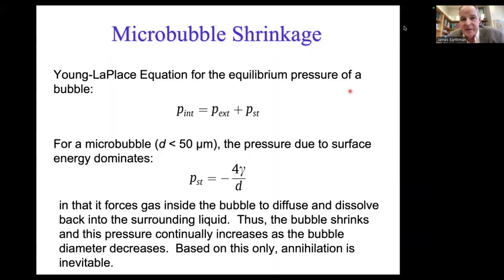The explanation for this is provided by the Young-Laplace equation, where you can see for equilibrium pressure of a bubble, you've got internal pressure, you've got external pressure, and then you have this surface tension pressure here. And again, when the bubble is less than 50 micrometers in diameter, that surface tension pressure is high enough to start pushing the gas out. The surface tension pressure is the surface tension, gamma, divided by the diameter of the bubble. So it goes up by 1 over the diameter of the bubble. And it's negative because it's compressing the bubble, making it smaller. This was the conventional theory at the time I started working on this. There was no way to explain why nanobubbles should exist.